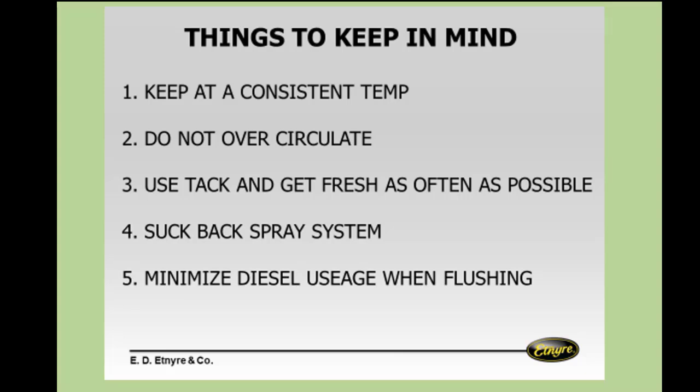The suck back of the spray system is very critical. People tend to suck back quickly, thinking they're getting things done. I like to recommend running it for longer than you think. It doesn't take that much time. And then minimize the release agent, diesel, solvent, or whatever you're using when flushing. There's only a small amount of material that you need to use. The other thing is when you're using tack at a lower rate per day and you're cleaning the bar all the time, you're running more solvents back into the material, so it does break the material down.